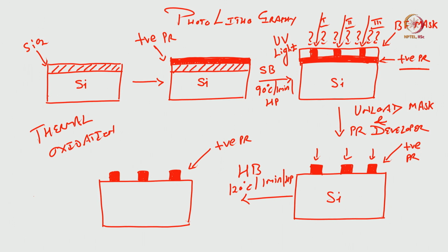So, on the silicon dioxide you have positive photoresist, and then there is a mask, and when you expose the photoresist with UV light followed by developing it, you get this pattern, and finally you end up with this pattern after you do the hard bake. Easy?